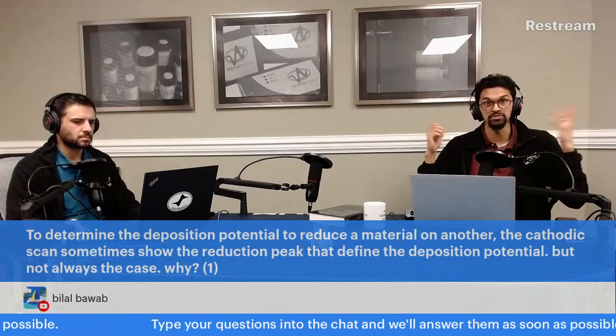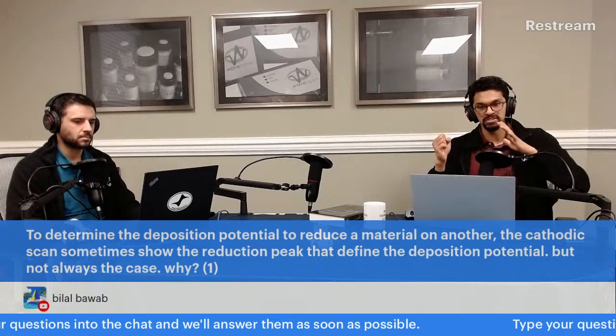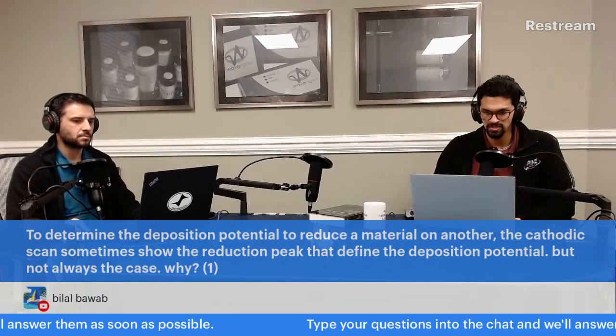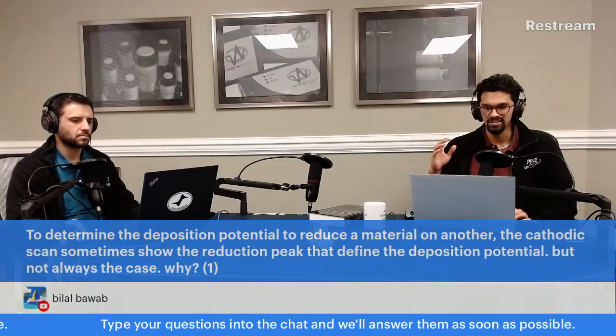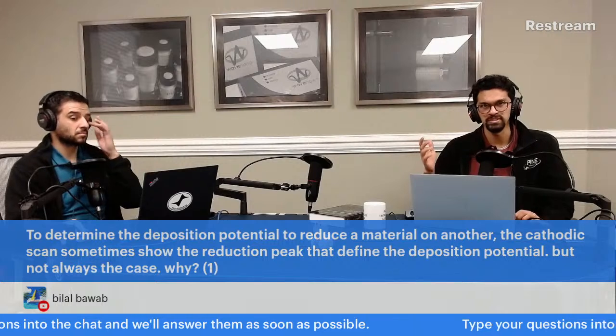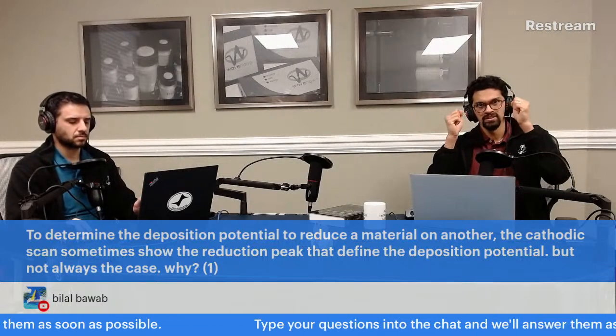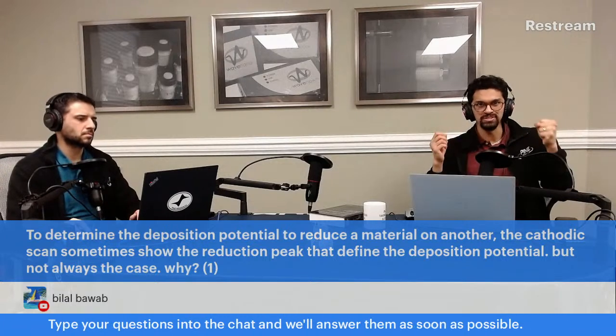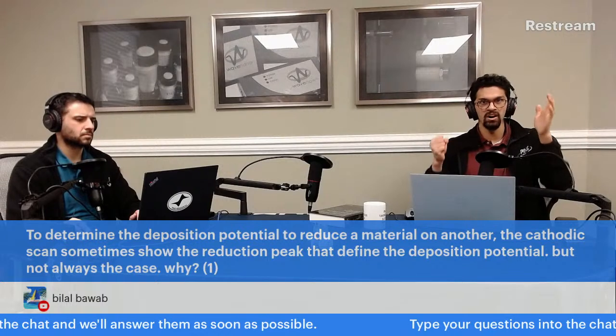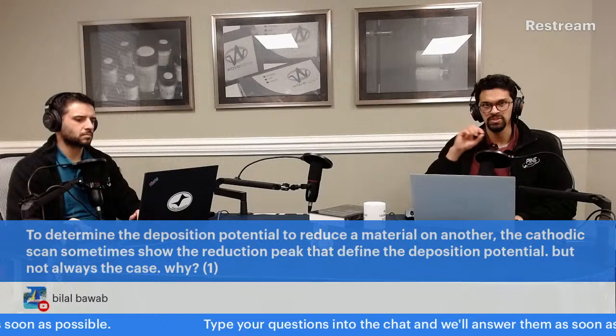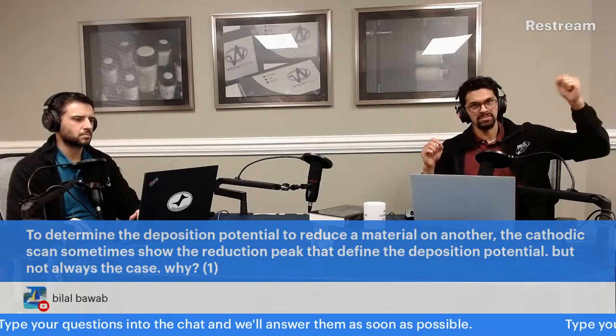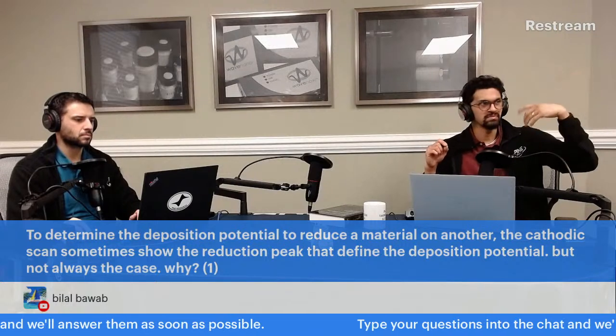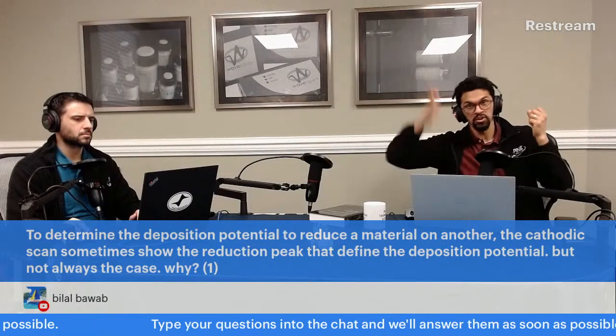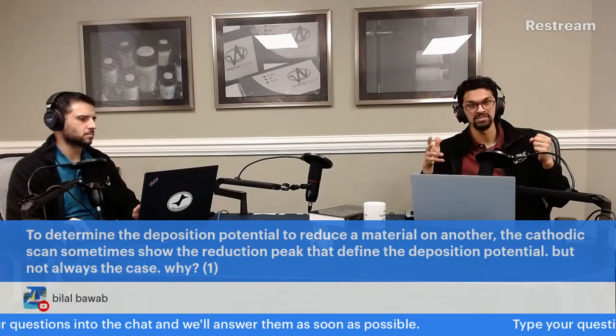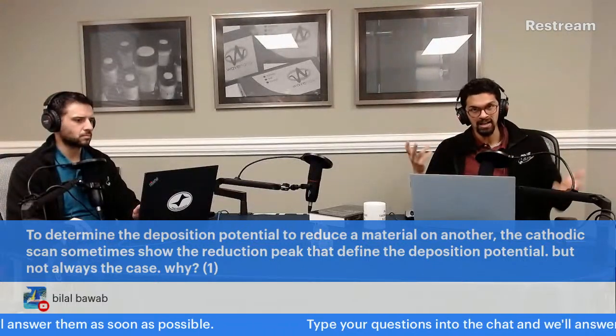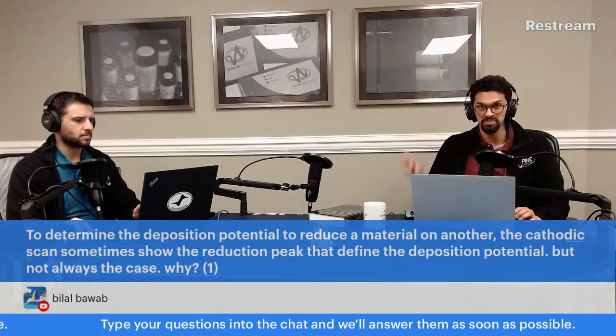Let's say maybe it's copper in the 2+ or iron in the 2+ oxidation state, and you're reducing it cathodically on the surface, and it's under potential deposition. When you're doing something like an over or an under potential deposition, it only works for that first layer, right? You're reducing one metal onto another, and there's a potential associated with that reduction. But the next time another metal, another iron or another copper, is approaching the surface, there's no more of that base metal or base material available. So you're unable to deposit any additional metal. You don't see a current, and hence your peak goes away.